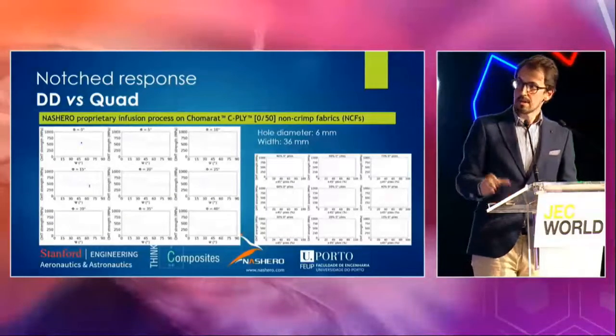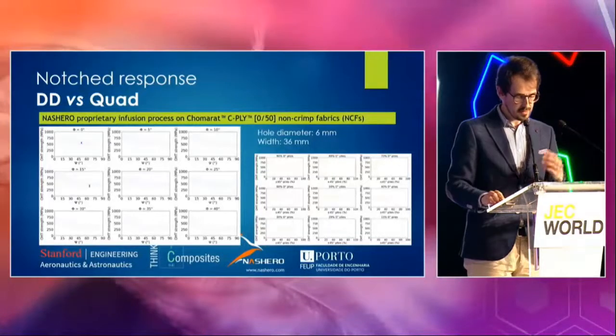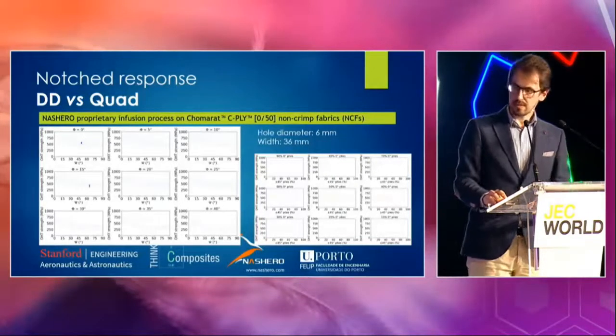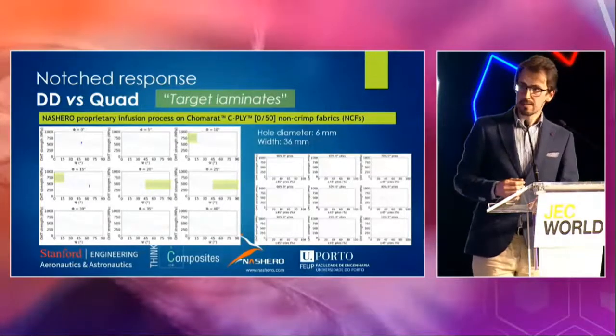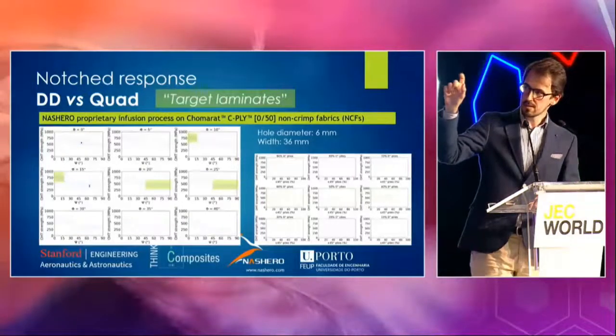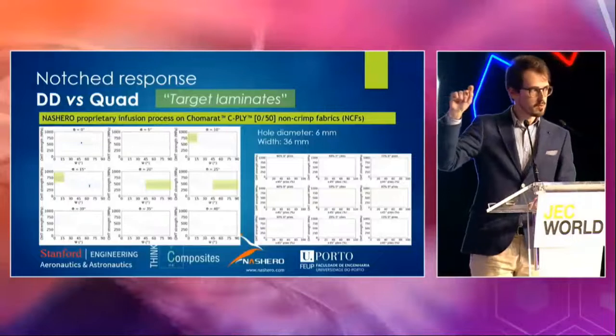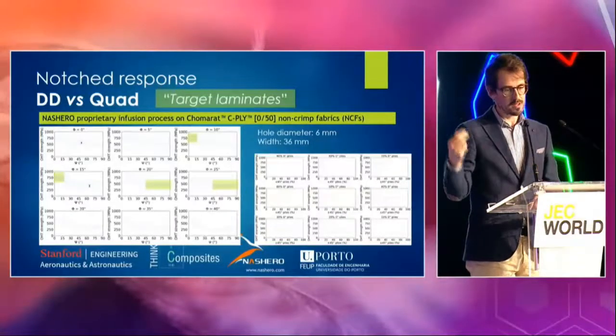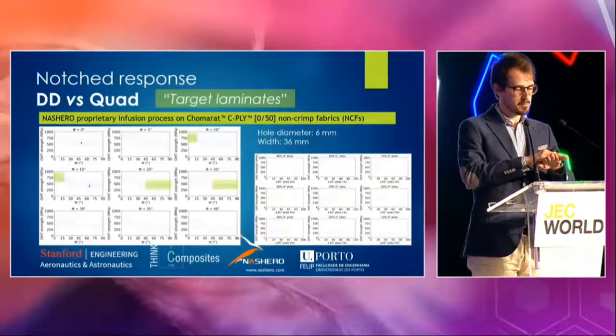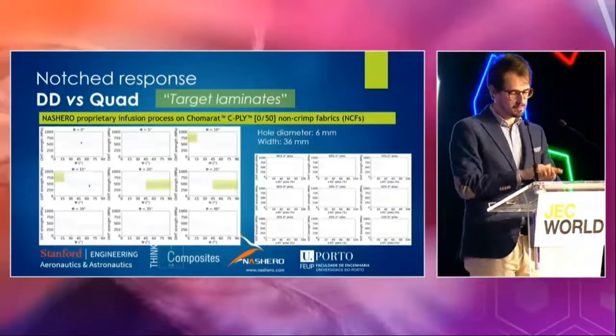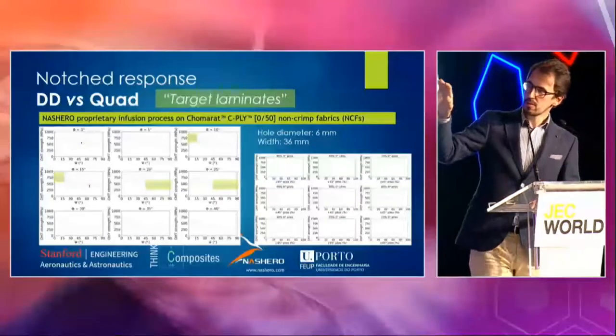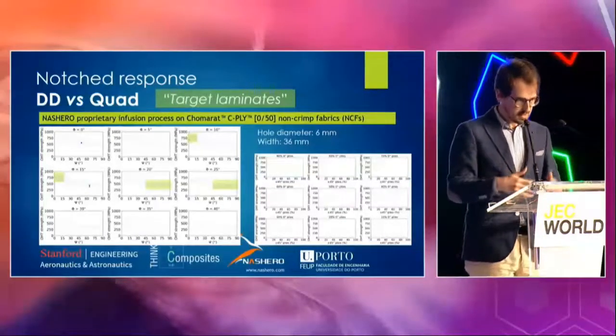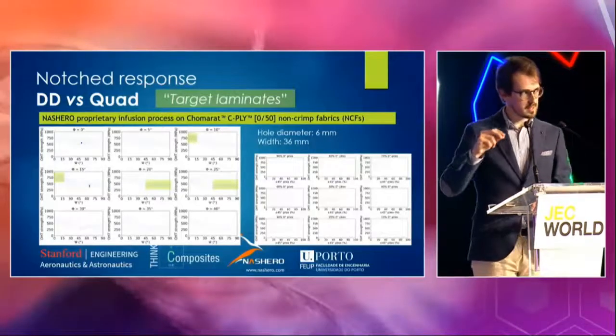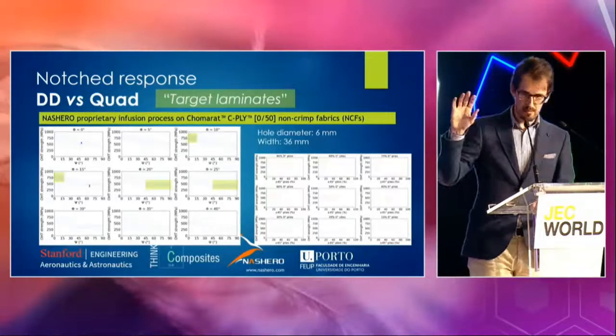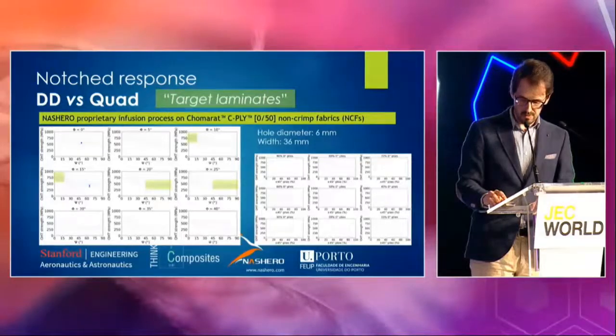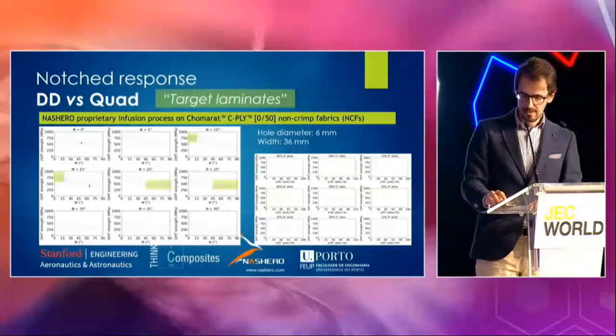Okay? In addition to this, if we pay attention to some of the curves on the left, we can even define other interesting concepts that can make certification rather easier, like, for example, the concept of target laminates, because you can actually see that for some particular angle plies, there is almost no variation of the notched strength, or in other words, the notched strength is almost insensitive to the angle ply, or to the double ply angle. Okay, which means that if you want to derive the design allowables for your structure, you can probably select one of these target laminates, because in terms of confidence of the data that you'll be getting, you are 100% sure of what you obtain, independently of the manufacturing technology that you're using.